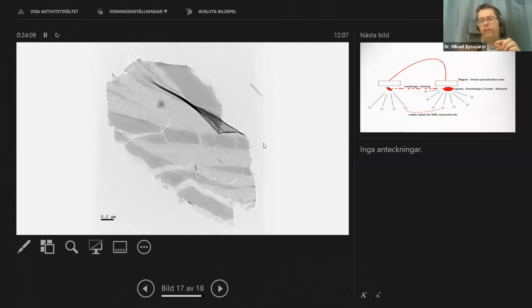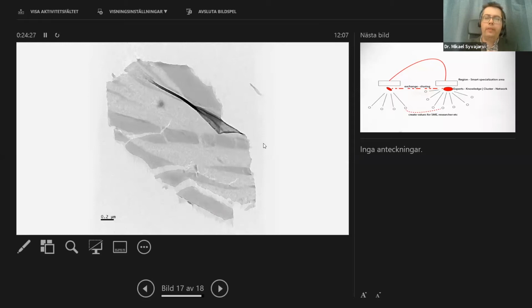But the graphene is not perfect in this type of flakes because it's slightly not planar. But you also see that it's not a symmetric shape. It has a little bit different edges and so on. So actually in this antibacterial function, it is these edges which kill the bacteria or make them a problem. So it's not a chemical reaction of the graphene, it is mechanical. So this is another avenue where the innovation came into new use, like in this case.